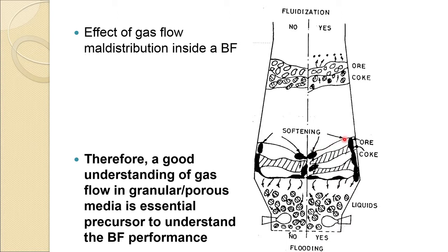However, or get semi-fused. So, the pores between the particles of ores get reduced. So, very less permeability, that is what we are talking about, the permeability, means quite a low void fraction in the gas in the ore region where it is semi-fused. So, this region is more about the cohesive zone where semi-fused material is there. So, gas is mostly passing through the coke. So, if the coke layer is not there separately, it is very difficult for gases to pass from here.